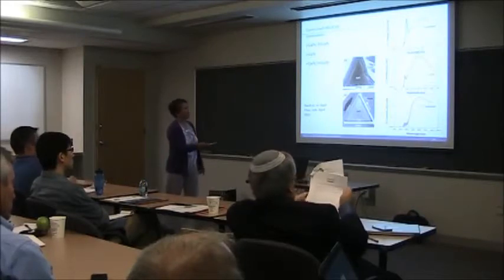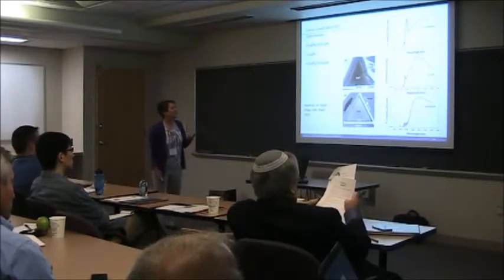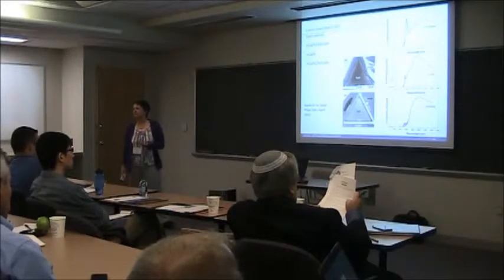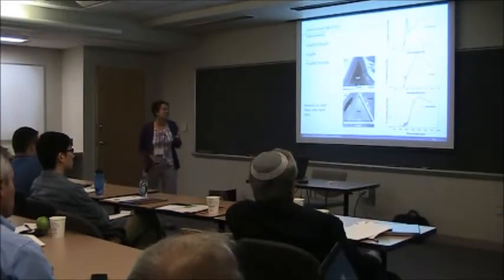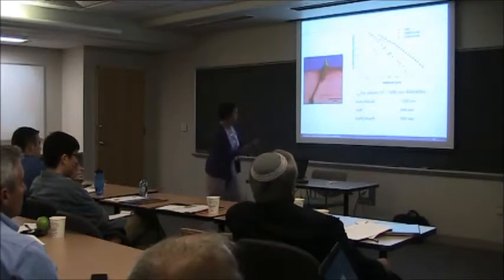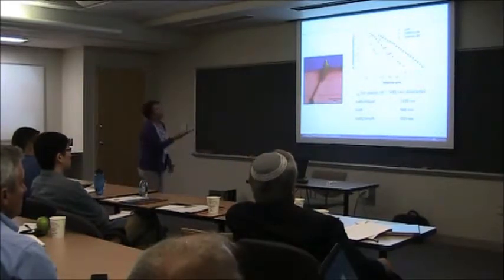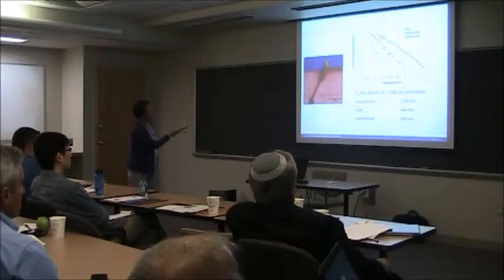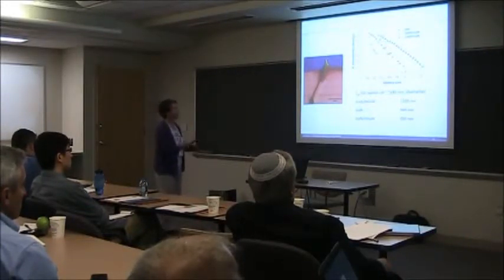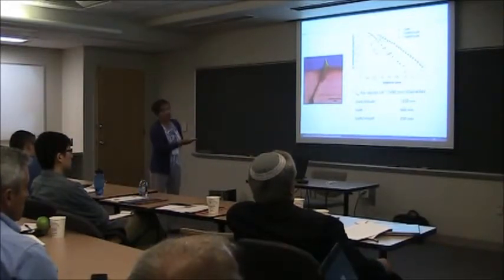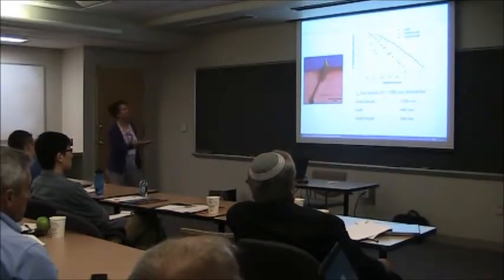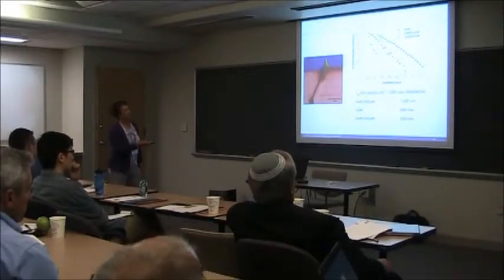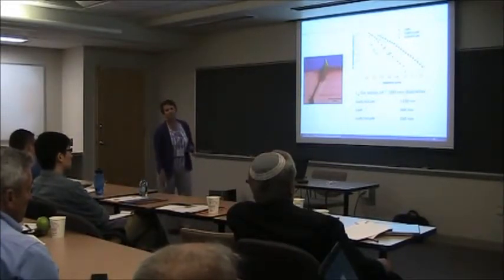And so very little. We're used to doing things like this, but from a transport point of view, it still leaves you saying, so what, right? Give me something a little more quantitative for transport. Well, now we can go in, take pictures like this, and plot the intensity as a function of distance from the excitation point. Put it on a log scale, exponential, if this is a good quasi-1D system. And so if we compare similar diameter structures, we get these minority carrier diffusion lengths. These are all doped wires, about a micron, 660 nanometers, 350.